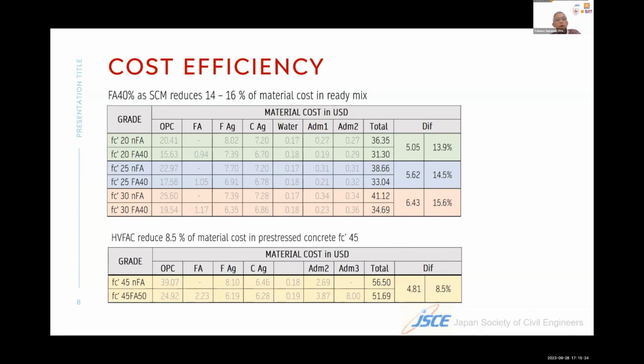And then for FC 30, if you compare between non-fly ash and fly ash 40%, we can reduce the cost by about $6.43, or about 15.6% of the material cost.